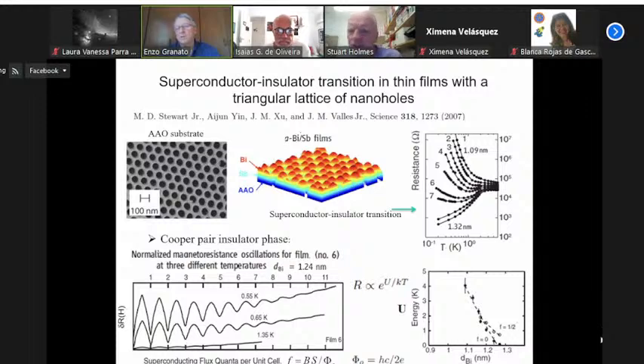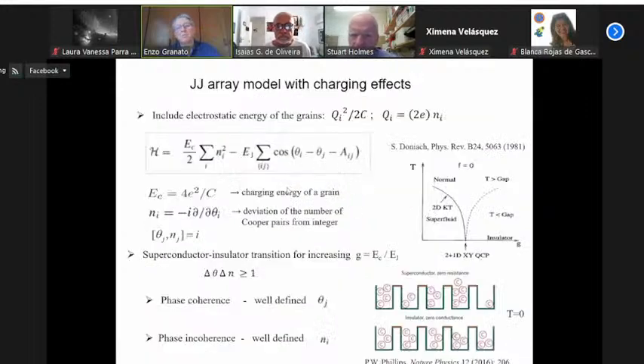No. Okay. In the graph you have here, the independent variable is the thickness of the bismuth. Now it's in the region where it's related to the de Broglie wavelength. Is it just a quantum effect that's coming? It's a quantum effect. Yeah. So the transition is essentially because of the quantum effect. In this model here, just because you have this first term here. If you don't have the first term, then if you go to very low temperature,